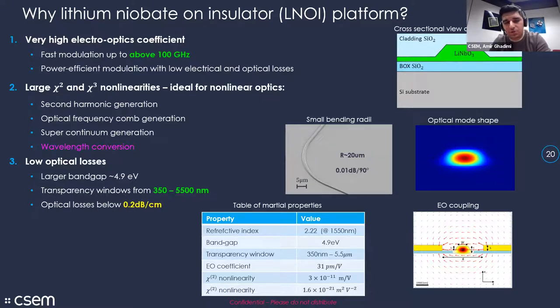And as I'm going to show you, it's a very low loss material as well. We are not even close, within a factor of 10, to the limit of the loss of the material. Normally, this 0.2 dB per centimeter is what we achieve, and it's limited by the sidewall roughness. I'll come back to this.